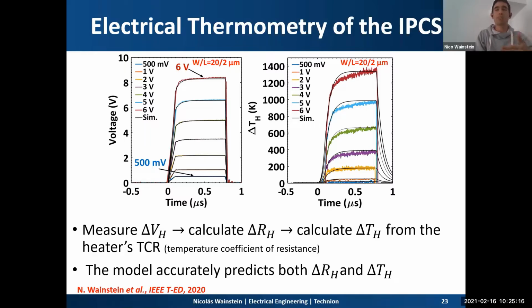Our model accurately predicts the temperature variation of the heater, as you can see here in the right panel, the black solid lines. Hence predicting the heater voltage as in the left panel, and the resistance variation of the heater within a 10% error. Note that in the right panel, the model predicts also the cooling time, which cannot be determined by this measurement setup, since the falling time of the voltage pulse is much faster than the thermal time constant. So a different method that I will show later on allows us to properly characterize this quenching time also.